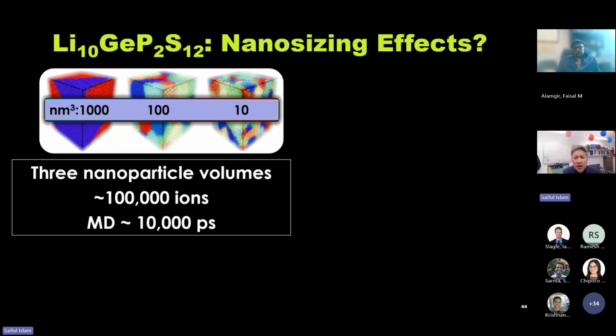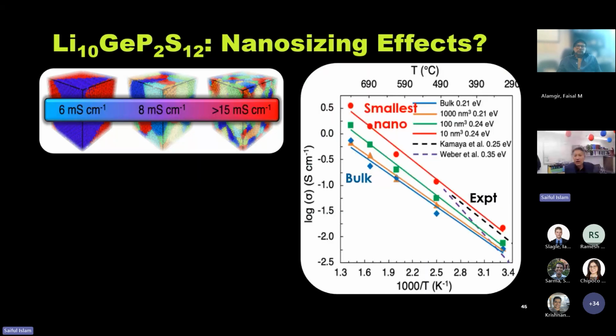So what did we do? We did some large scale MD, nanoscale modeling of 3 nanoparticle volumes. And we're doing large scale. We can't do this with DFT. Look at that, 100,000 ions we're modeling, and MD up to 10 nanoseconds, 10,000 picoseconds. So what do we find? It's always sad to represent lots of hours and hours of work in this way. And this is work beautifully done by James Dawson, who's now on faculty at University of Newcastle in the UK.